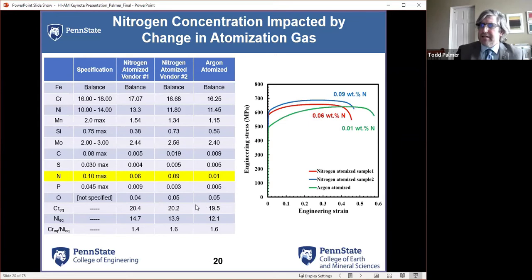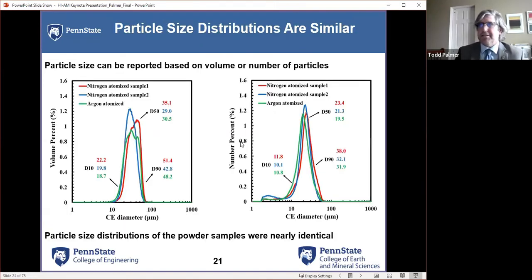So what it gives you is an idea of the other alloying elements that might contribute. Chrome is a ferrite stabilizer, nickel is an austenite stabilizer, and so how these different alloying compositions can impact that. And what we tend to see here is really the impact of the increased nitrogen levels versus what we see in the argon atomized.